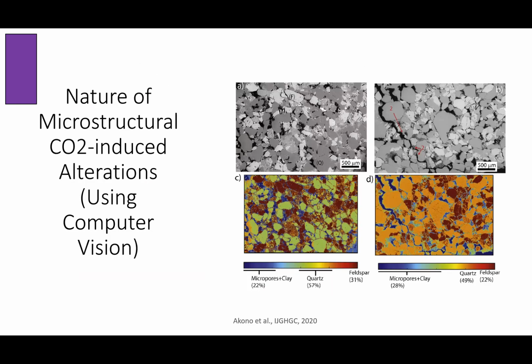Okay. What is really interesting is one thing that we tried to do was to use computer vision and to see, using computer vision, are we able to have the same conclusion regarding microstructural and mineralogical alterations? So what we did was, again, to have kind of this large mapping using backscatter electron microscopy. And then we can use image analysis and use a different gray level to identify different phases. For the phases, we had feldspar, we had quartz, and we have micropore and clay, and that's really based on the gray levels. And we can see what happens.